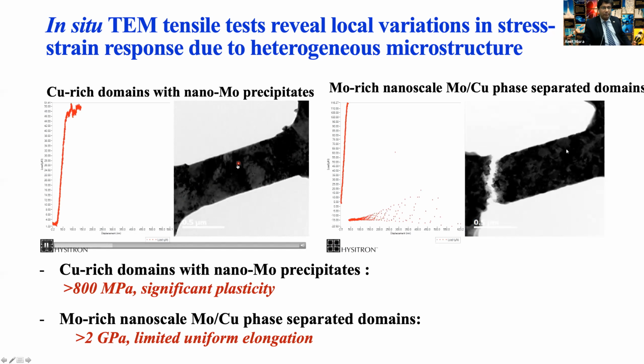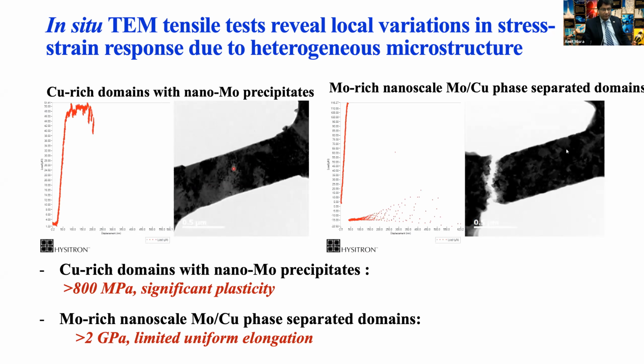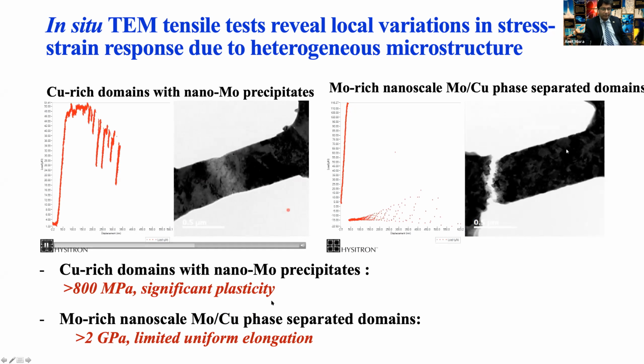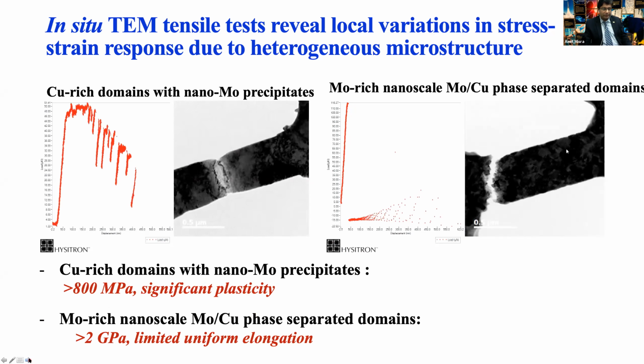So this is the copper domain with nano moly precipitates. It has higher plasticity. So you can see that most of the plasticity is coming from these relatively softer regions. It is still pretty hard compared to pure copper. Whereas the moly-rich nanoscale, which is very fine scale, behaves more like the multi-layer, which is very high strength, but limited uniform elongation. But together, they are able to produce a much better composite response of strength and deformation.